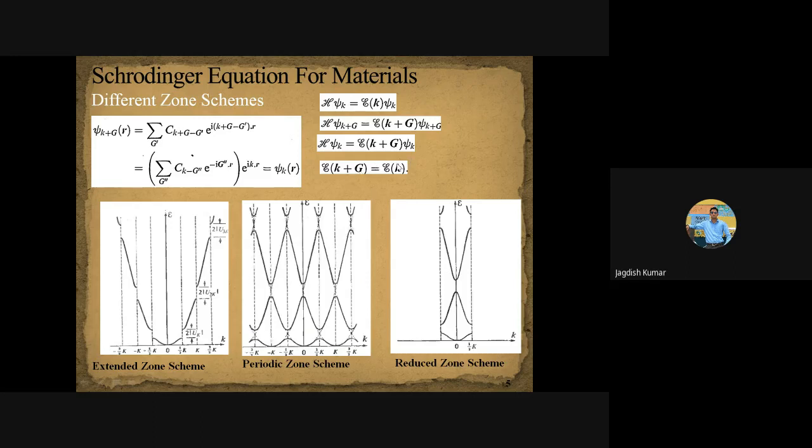This is the basic property which allows us to do this. So this part is the information of E versus K taken from the second Brillouin zone. This part is the information of the E versus K relation taken from the third Brillouin zone, and so on. So here is how we can represent the whole band structure, or the whole E versus K relation for an electron in an infinite size reciprocal lattice, in only the first Brillouin zone, and that is what we call the reduced zone scheme.